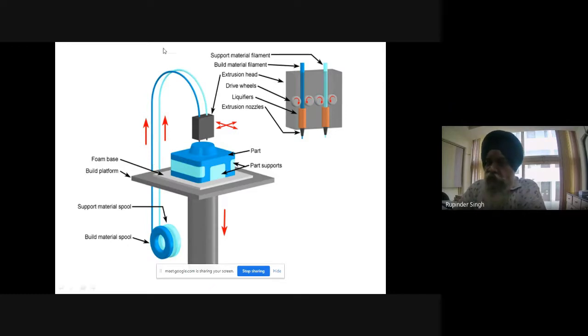Once this feedstock filament is fed into the liquefier chamber, there is a nozzle, and through this nozzle the larger diameter is converted into a smaller diameter. Depending upon the nozzle, you can have the output as 0.2, 0.4, sometimes 0.25 mm, right? So the thick wire is fed through a feed mechanism into the liquefier head, and I get a fine strand of wire.